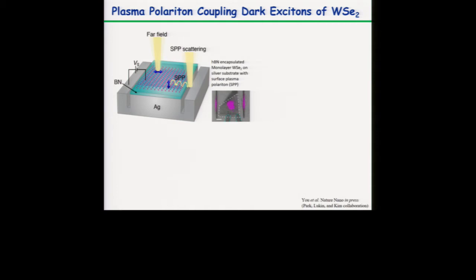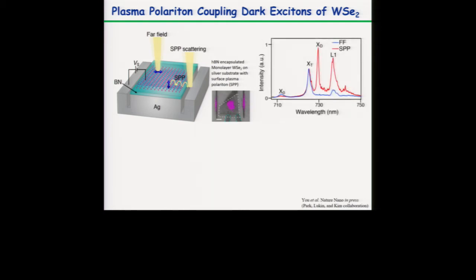Okay, but then this is another part. We can also couple TMDCs to other materials, or we can also couple them to plasmon polaritons. Like we can couple them to silver. And plasmon polaritons have out-of-plane polarization. The electric field is out-of-plane. So if we look at the PL spectra, we are exciting PL in this spot, and we can also collect in the same spot. That's far field. This is the blue spectrum, where we can obtain the neutral exciton and the trion.